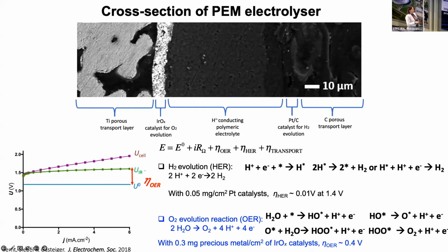The problem is more the oxygen evolution reaction. And you see here there are 4 intermediates, and you need a catalyst, first of all, to break the scaling linear relationships between all these intermediates, but also something that is stable. Iridium oxide is just about the only catalyst that is stable now, and you still need quite a lot of it. And as you know, iridium is expensive, and so that adds to the cost of the electrolyzer, together with this bipolar plate.